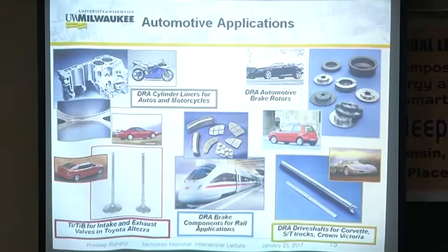These are the components in automotive. This is a cylinder liner of Honda Prelude. You see, here is the reinforcement here, and this is made by a single step pressure infiltration casting. In one shot you produce, and you see here the fibers are reinforcing, and this allows you to make the engine smaller and lighter. Okay, the brake rotors in many cars, they used to be cast iron, but if you make them out of aluminum silicon carbide, they are only 65% of the weight.